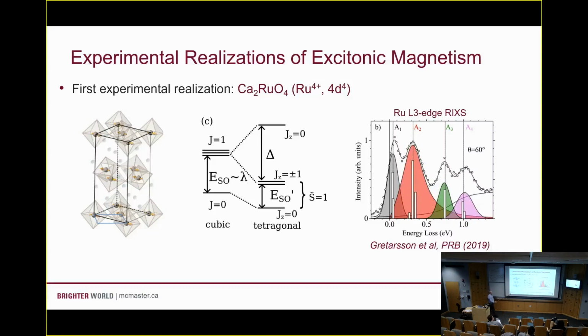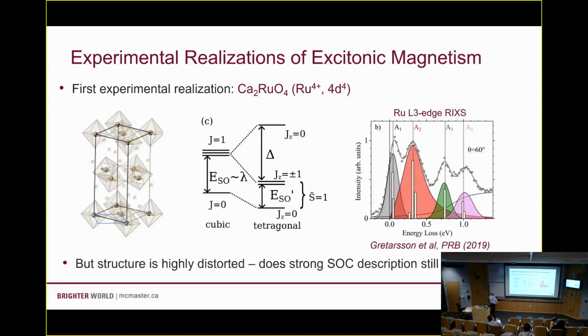Okay? 4d4 system, and you can look, again, you can see these energy levels, and you can see the magnetic order that corresponds to these excitons formed. Okay? So that's great, except for the fact that if we look at the crystal structure from X-ray diffraction, or if we look at these energy levels from RIXS, what we find is that the structure is very highly distorted.